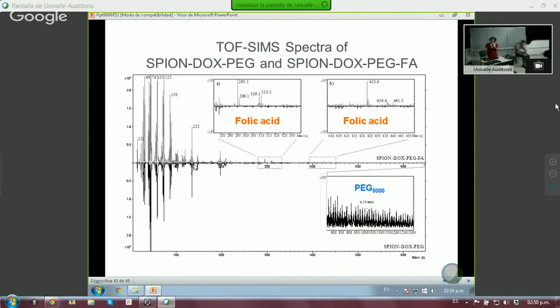Now, when we go to the TOF-SIMS, this is the kind of spectra that you get, and you have to analyze it. And what is interesting is we looked at the folic acid by itself, which we took from the literature, and this is the result you get. And here we have the PEG 5000 and so on. So anyway, we could identify all these peaks, but again, we didn't go into the calculations.